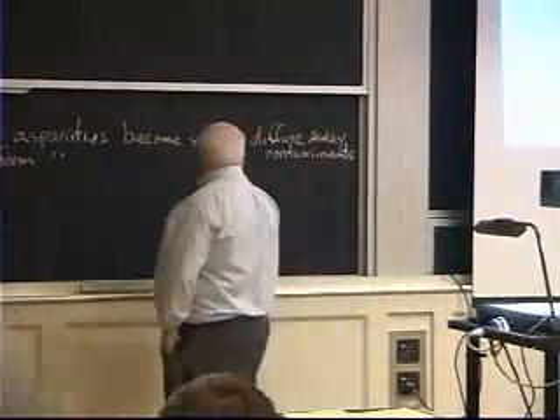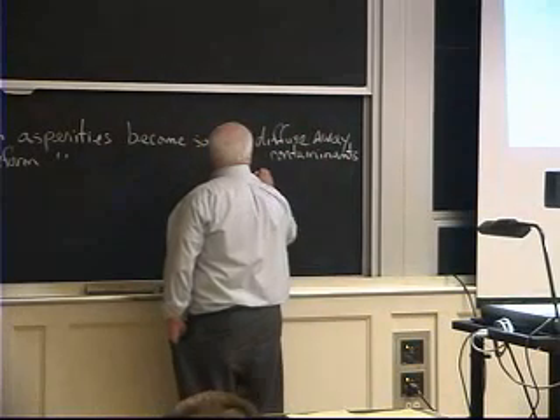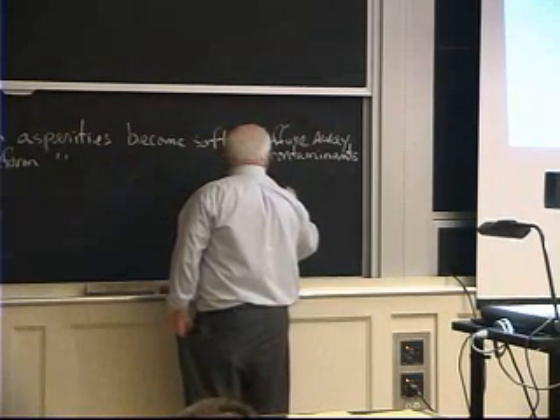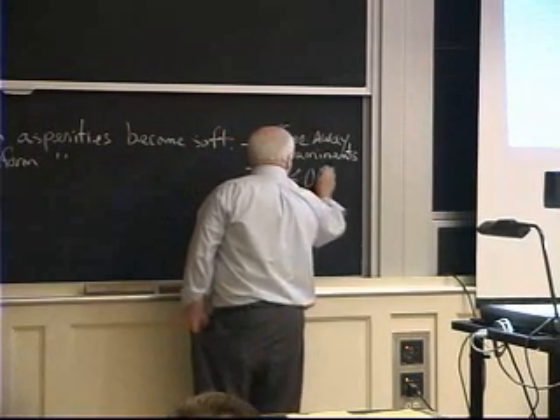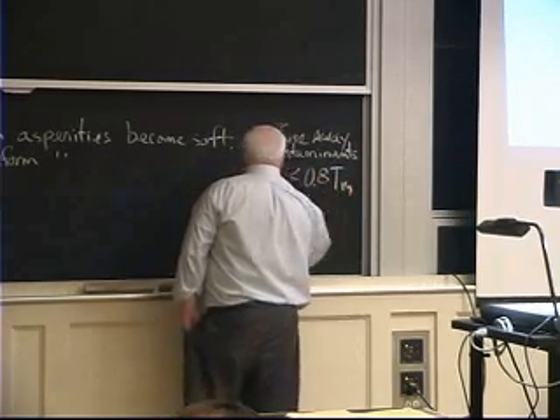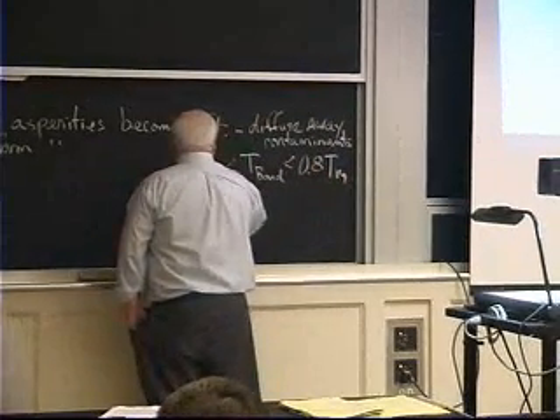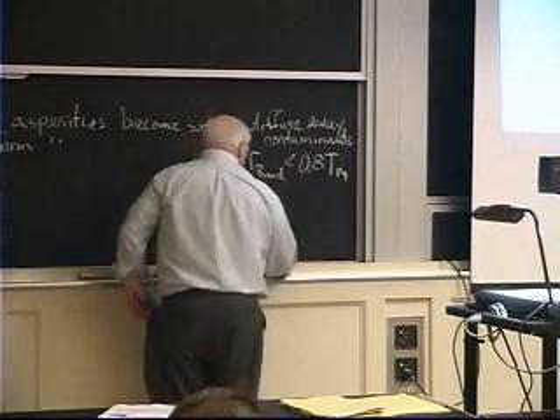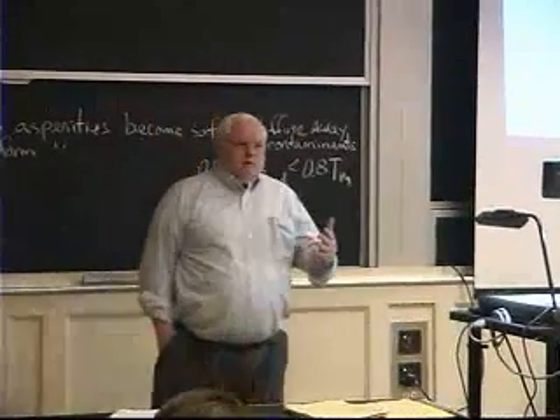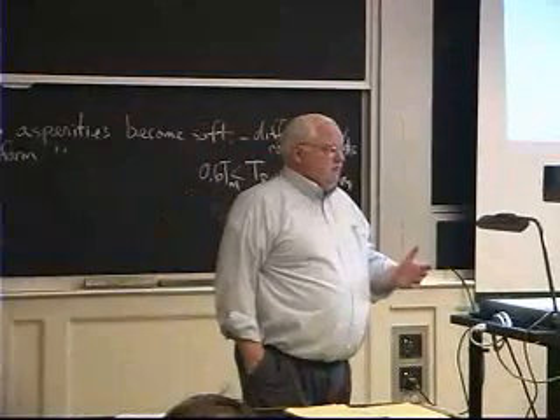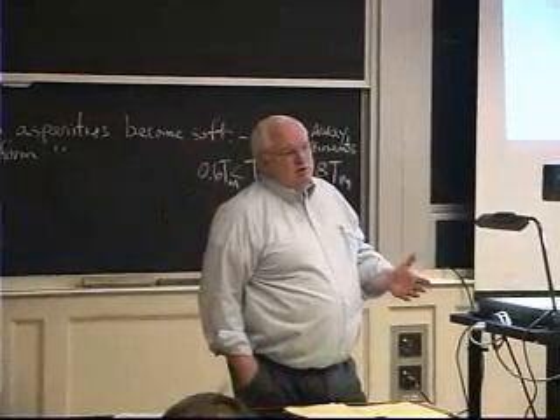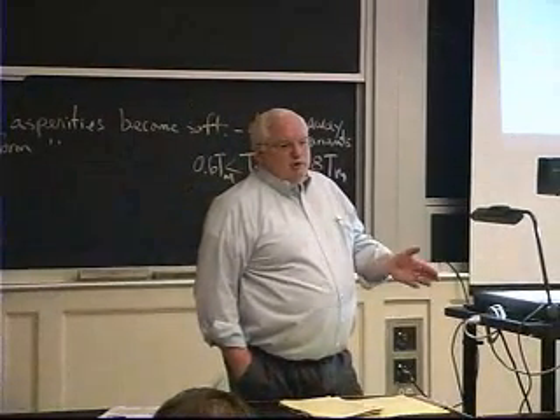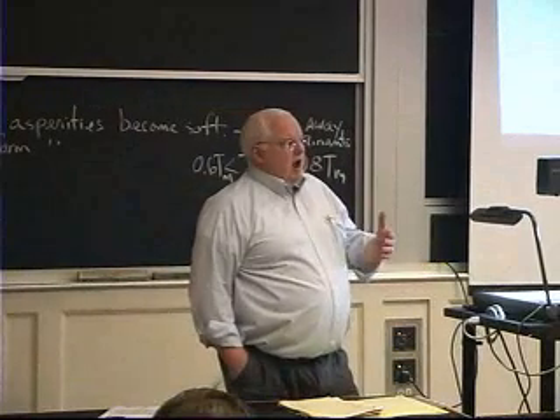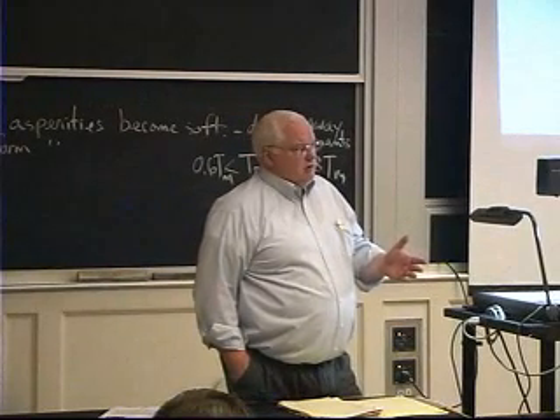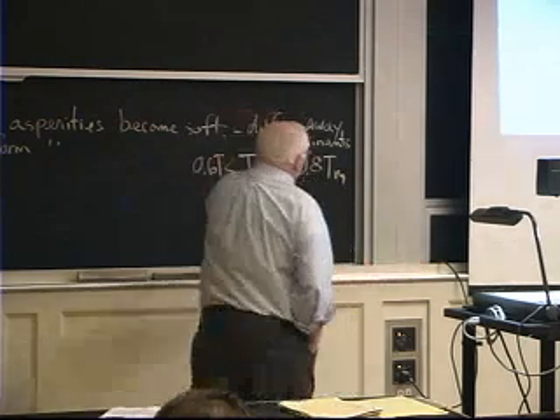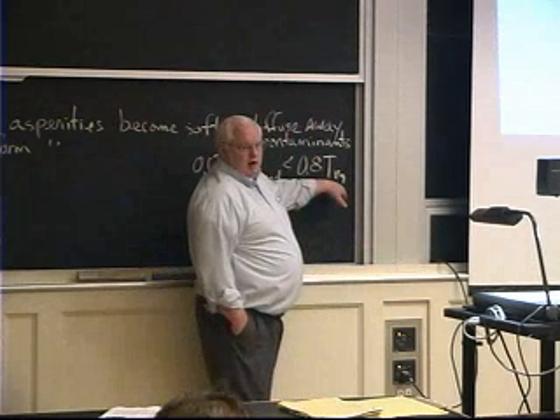The types of temperatures that we use, T of bonding, is less than 8/10 of the absolute melting point and greater than about 6/10 of the absolute melting point. What do I mean by absolute melting point? Well, the melting point of lead is 327 degrees centigrade, but that's 600 degrees Kelvin. I had 273 to 327. Lead has an absolute melting temperature of 600 degrees Kelvin. So when I'm talking about melting temperatures here, I've got to be in absolute values.